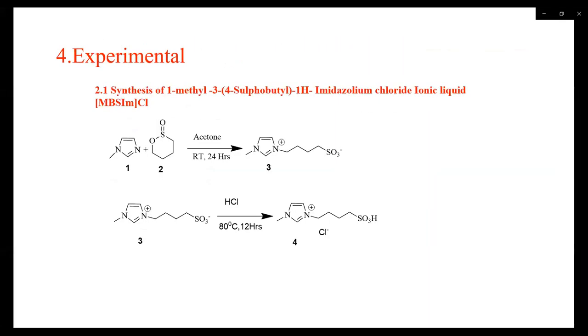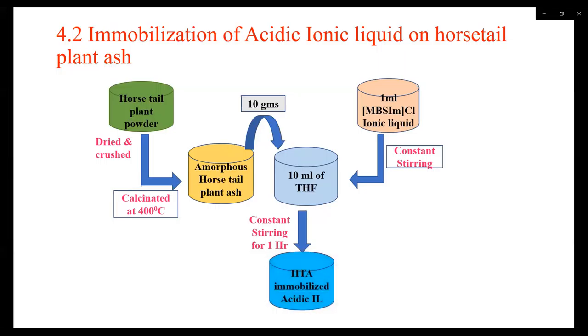In the present work, we have synthesized 1-methyl-3-sulfobutyl imidazolium chloride ionic liquid using 1-methylimidazole and 1,4-butane sultone under reflux condition, and further reacting with concentrated HCl gives the respective ionic liquid. Our second objective of work is to immobilize this acidic ionic liquid over a naturally occurring solid support, that is horsetail plant ash, which itself acts as a Lewis acid.